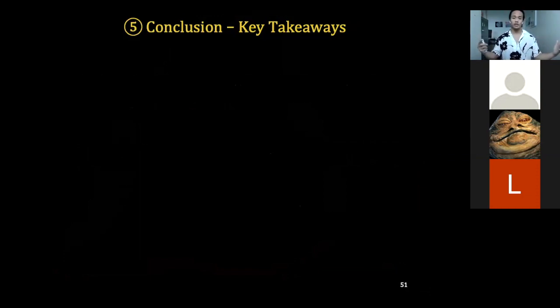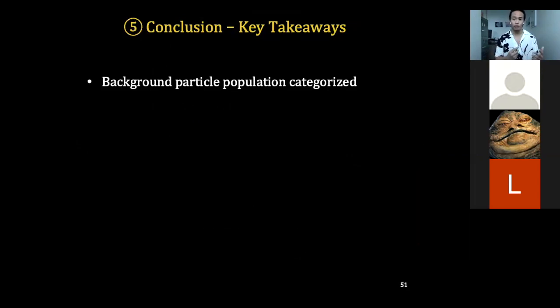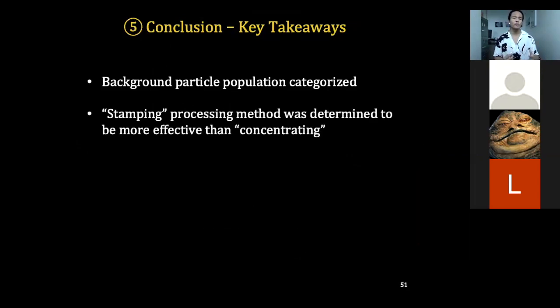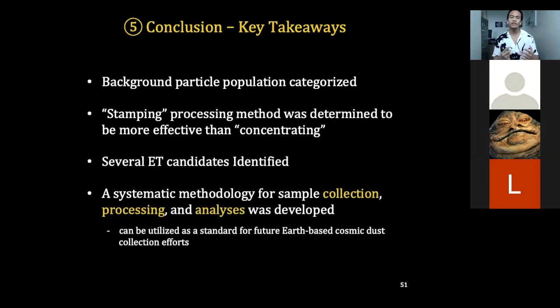Some of the things that we were able to achieve include, we were able to categorize the background particle population. We were able to determine that the stamping processing method was more effective than the concentrating method because it didn't have the water washing that contributed to the loss of the soluble particles and contributed to particle breakup. We were also able to identify several ET candidates, and although that one particle that we analyzed turned out to be not an extraterrestrial material, we were still able to develop a systematic methodology for sample collection, processing, and analysis during the course of this project. This methodology can then be further refined and be utilized as a standard for future Earth-based cosmic dust collection efforts.